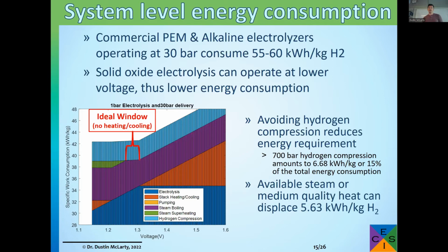If you're lucky enough that you have available waste heat or geothermal heat that's at 400 degrees, you could actually displace all of that in a high temperature electrolyzer in a way that you couldn't in a low temperature electrolyzer. So it's another way to reduce the energy consumption by another 10 to 12% if you have readily available waste heat.